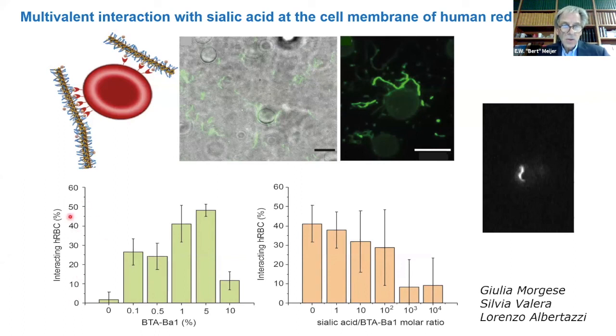And to see it over here, you see a graph on the bottom. This is how much of the functional unit we have to add to the polymer. If there's nothing in, it doesn't bind, but then we go to 5% and that is the best possible way to bind. And if you add more to this, the cell gets a problem to figure out how to deal with all of these functionalities. In order to show that it is really a multivalency effect, you see here how much free sialic acid we have to add to this cell supramolecular polymer area in order to remove the fiber again from the structure. There's 10 to the power 3 to 4 times more free sialic acid than sialic acid on the supramolecular polymer that breaks up this type of interaction. For us, it's a very appealing way of using this type of methodology in order to go to the artificial extracellular matrix.